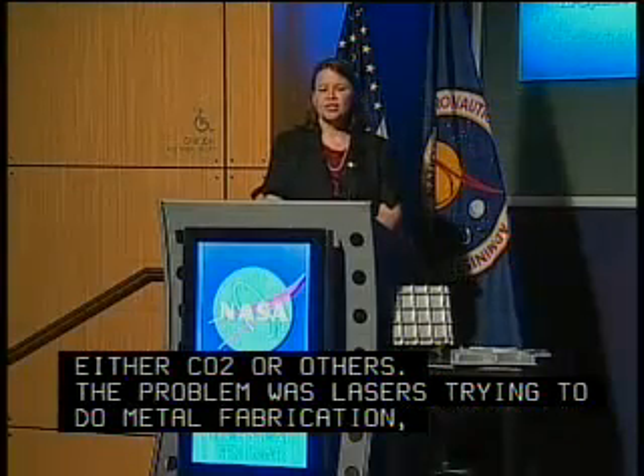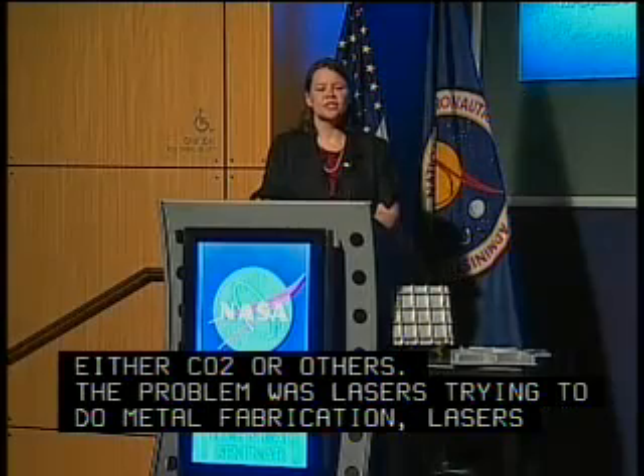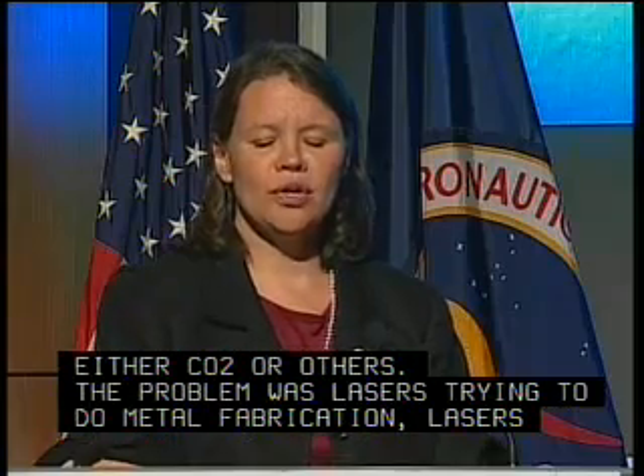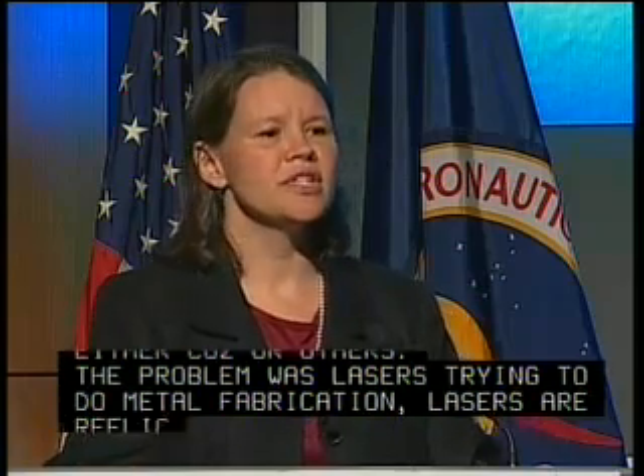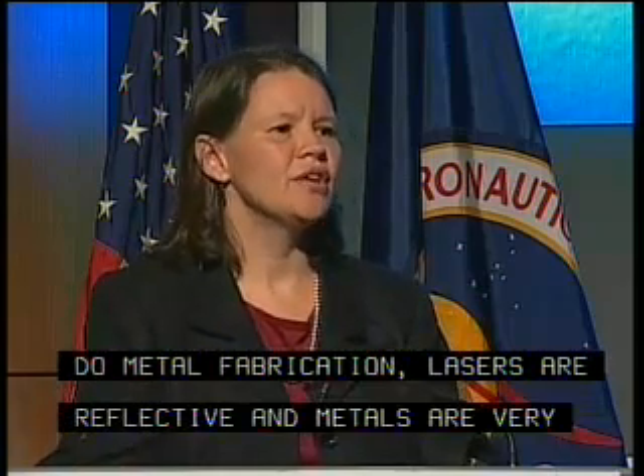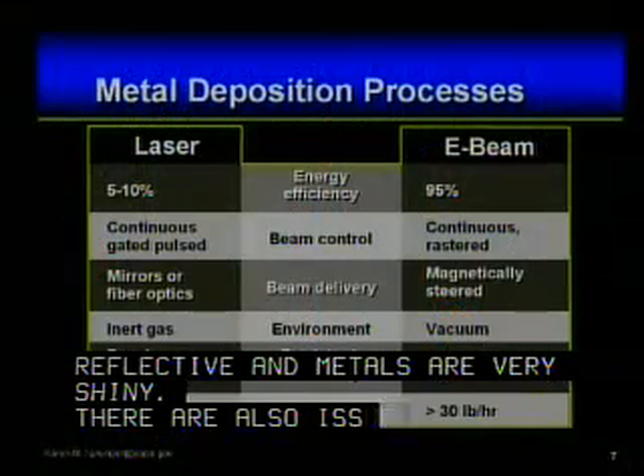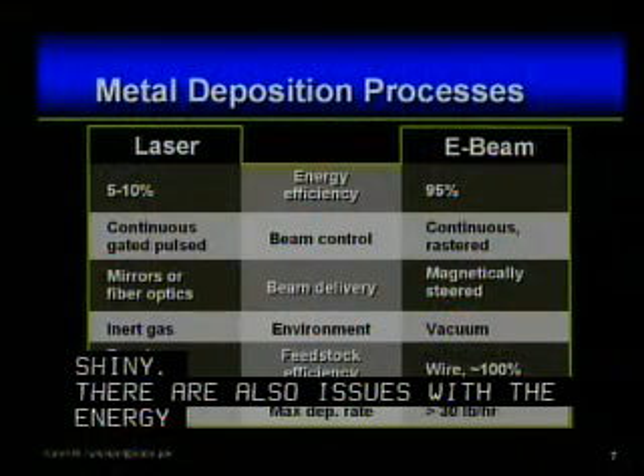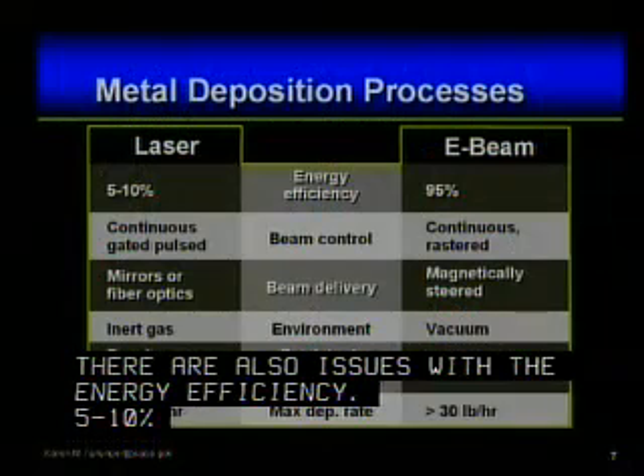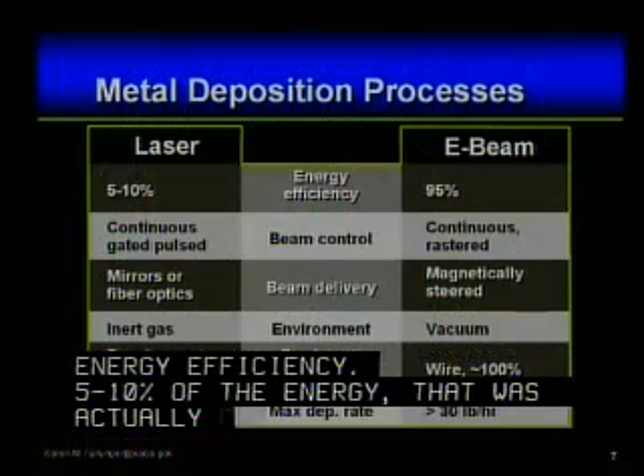In addition to the coupling efficiency between the laser and the metal to be able to melt, there are also issues with the energy efficiency. Only 5 to 10% of the energy, and this has improved over time, but in 2001, only 5 to 10% of the energy that was actually pulled from the wall ended up being used to create the beam. The rest was all waste heat.